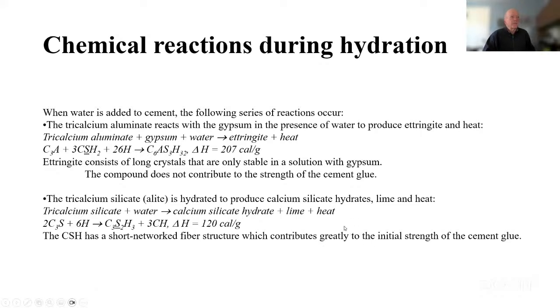Okay, and this is a description of actually what happens when you add water to this cement. Here's kind of what happens in sequence. So the first thing that happens is this tricalcium aluminate and gypsum and water react together, and it forms these crystals that are only stable in a solution with gypsum, and it does not contribute any strength to the cement. Okay, but what it does do, you can see the amount of heat that it releases. So it releases a fair amount of heat or energy per gram of reactants.